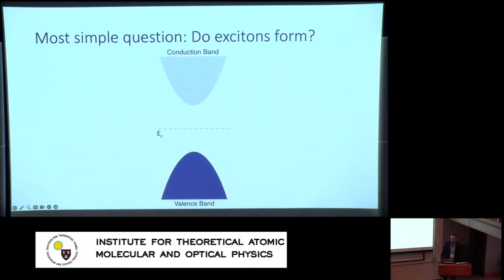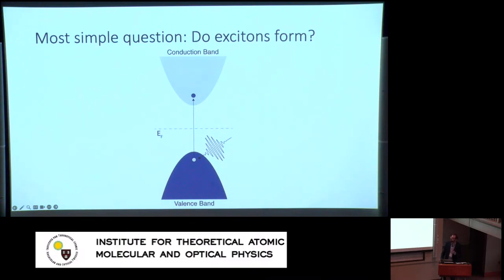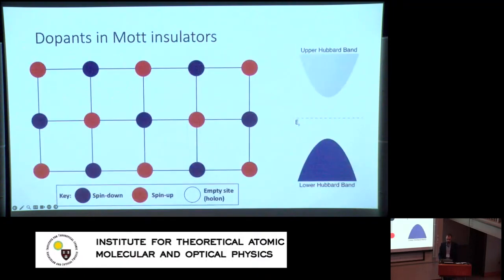In a semiconductor, we know that when we drive the material, initially you're going to create a hot electron-hole plasma, so the system will become metallic. Then as these carriers cool towards the band edge, their recombination will be bottlenecked by the fact that there's a gap. So in the interim period, to lower their energy, they'll emit a smaller amount of energy and form an exciton. This exciton is like an intermediate favorable state between photo-excitation and recombination.